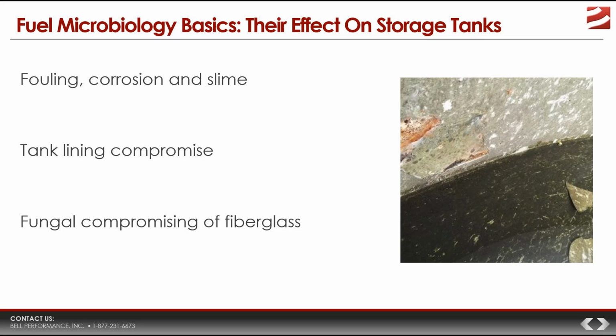And microbes like fungi can also compromise fiberglass tank surfaces simply by establishing themselves on the surface, then penetrating the resin, and then consuming the resin, which deplasticizes that fiberglass, creates more gaps for additional microbes and for additional moisture to get in there, and now you have a huge problem. So those are the kinds of non-corrosive damage issues that can happen in storage tanks with microbes.